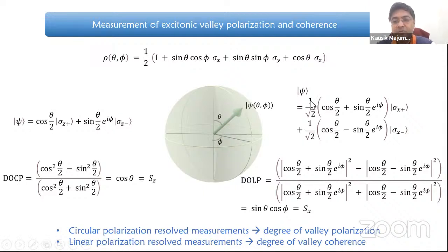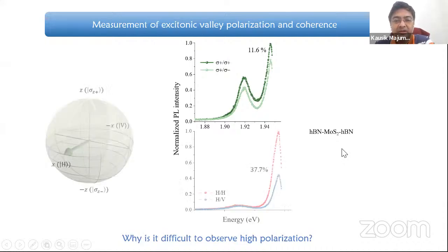On the other hand, if I excite with linearly polarized light, I can write it in the basis of the linearly polarized states, say X, and then I can find the degree of linear polarization. That directly corresponds to the degree of valley coherence. Okay. So with that in the background, if we try to measure this kind of co- and cross-polarized valley polarization and linear polarization, in both cases the typical numbers we see are fairly low, like this is 11% and this is 37%. There's a reason why linear polarization, or the valley coherence, is easier to maintain compared to the circular polarization. I'll come back to that later.